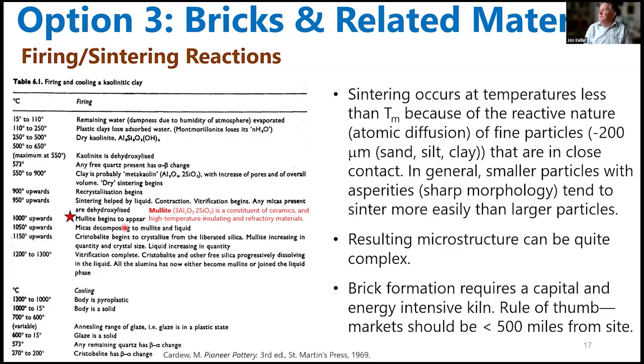And this sintering process is occurring at temperatures less than the melting temperature because of atomic diffusion. Typically it will have fine particles less than about 200 microns. So it would contain those definitions earlier, sand, silt, and clay particles that are in close contact. And the sharper the particles, the better in terms of getting sintering to occur. The final microstructure that results can be quite complex.